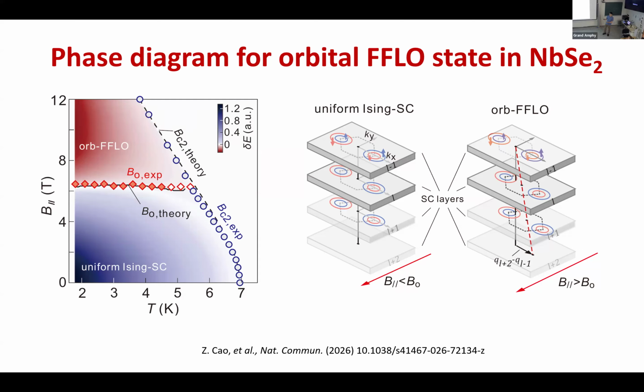So for these samples, the starting point is a bilayer with the in-plane field introducing some vector potential to shift your momentum. Now we have many layers. Our theoretical collaborators gave us this picture that, again, this is just shifting one by one. This is a bit different from what the other group in the beginning claimed, that you have opposite shift in between the layers. Here, we believe the momentum shift is uniform, monotonic. So for example, the layer lower below shifts to the right-hand side, and then the other one shifts further to the right-hand side, and so on. So an intuitive understanding of why such a transition between the momentum states should be first order.